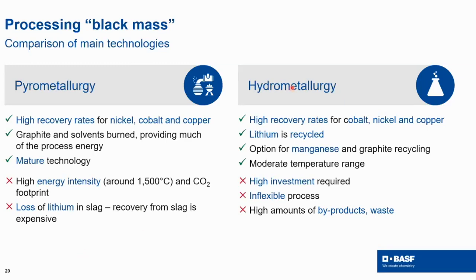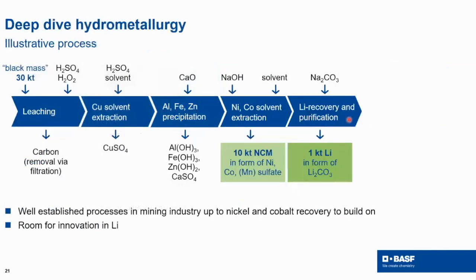Hydrometallurgy is a cold process. It also has high recovery rates for cobalt, nickel, and copper. And there lithium is also recycled, and manganese recycling is also possible. The drawbacks of hydrometallurgy are the high investments required and the high amounts of byproducts. Nevertheless, because of the temperature profile and the lithium and the manganese, this is a process where we build on at BASF. I would like to show you one typical process of hydrometallurgy as it is used in the battery recycling industry, and then elaborate a little bit on the improvements and adjustments which are necessary.